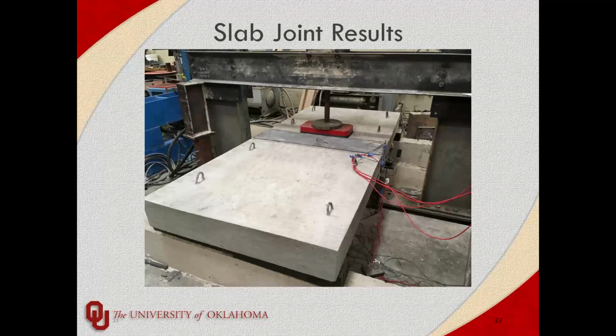This is our slab setup. So the two together, about an 8-foot span. The joint is about 12 inches wide. And then we applied the load through what was meant to recreate a wheel load just to the side of the joint. And as you can probably tell with this picture, that Ductal is poured just ever so slightly higher per the recommendations. We didn't grind anything off, we just kept it that way. But we also poured J3 similarly just to try to maintain similarities. But the load was put just to the side of the joint to help maximize the load applied at the joint interface.